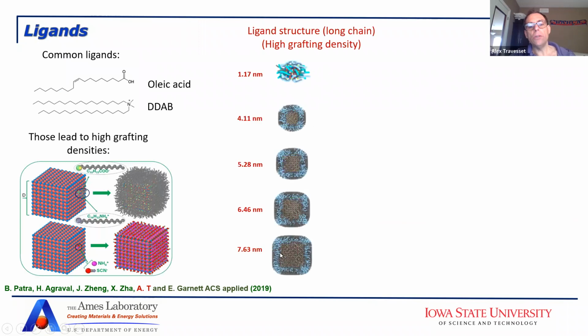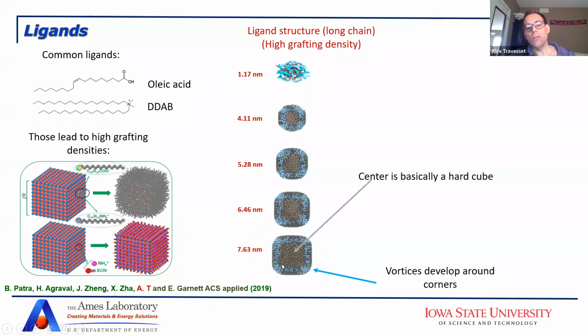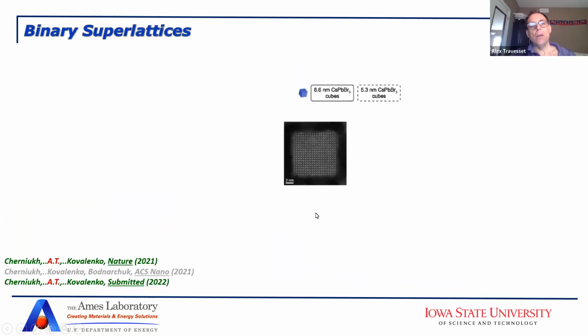And we've done simulations. And here what you see is that in general, if the density at which you pack them is very high, you still develop vortices around the corners, but in general, the center behaves as a hard cube. So even at a very high packing fraction, in a high packing of the ligands with the cubes, you can form a very hard cube, but you will also be able to form vortices at the corners and even at the edges and so on. So with that, let me tell you what the experiments tell us.